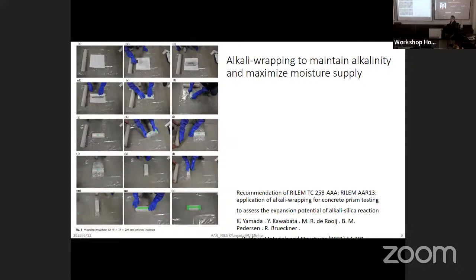I added some explanation here, but it was gone somewhere. But anyway, the procedure is like this. We prepared some water holding material. And in this paper, we poured alkaline solution having the same pH as the pore solution. Then with this paper, the concrete prism is wrapped like this. By doing this, at the timing of length change measurement, water is consumed by the alkali-silica reaction, then the reduced amount of water is re-added. So we can provide sufficient supply of moisture, maximum supply.